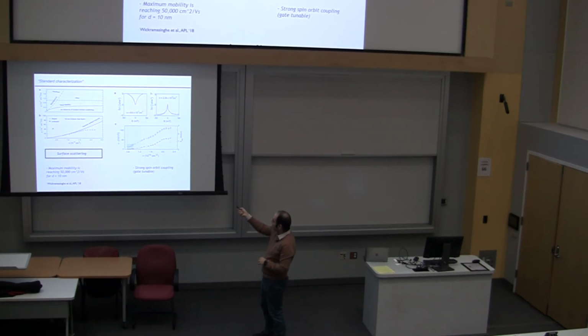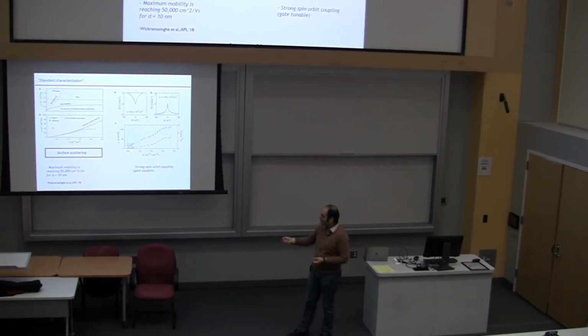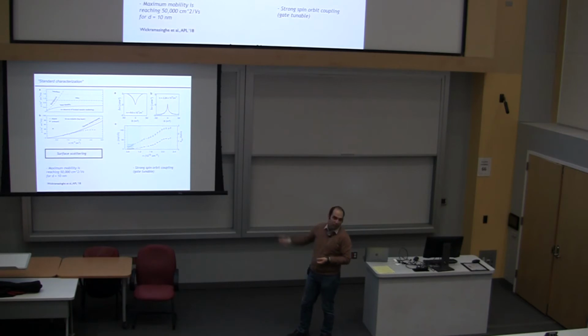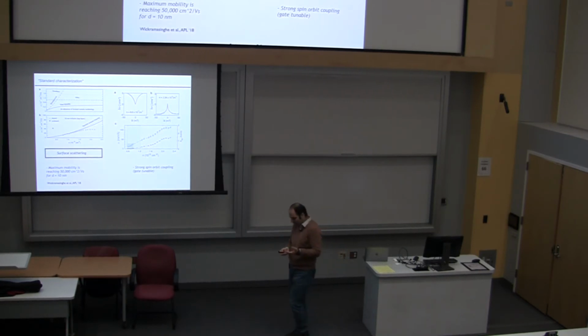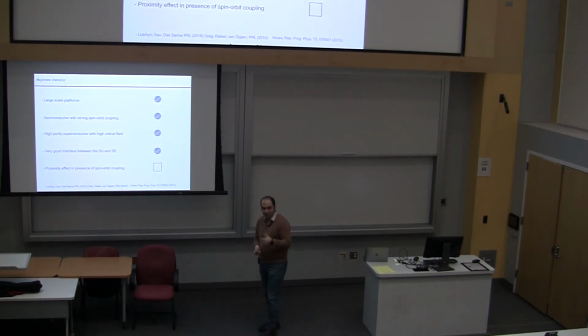So this is the correction to the conductance as a function of magnetic field. You can fit it, you can get numbers. If you change the density, alpha as a function of density keeps going up, right? So that's good. It's the standard characterization and all that.